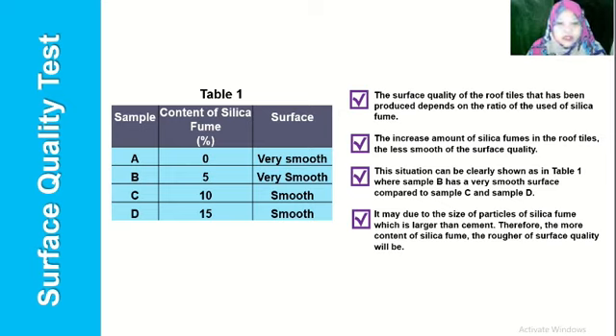Okay, table 1 here shows that the surface quality of the roof tiles produced depends on the ratio of silica fume used. The more silica fume in the roof tiles, the less smooth the surface quality. This can be clearly seen in table 1, where sample B has a very smooth surface compared to sample C and sample D. It may be due to the particle size of silica fume, which is larger than cement. Therefore, the more silica fume content, the rougher the surface quality will be.